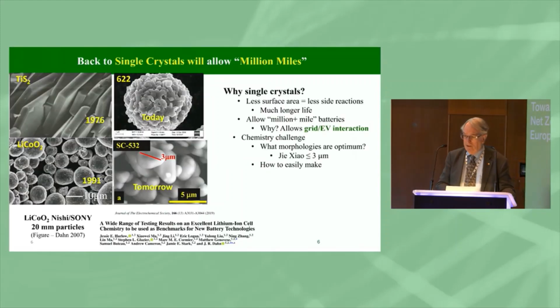Now, single crystals. What we're going to be doing is really going full circle if we do that. Here is Exxon 1976 single crystals. These we measured millimeters on the side, and if we wanted, we could make these centimeters. The commercial batteries all were millimeters on the side. Sony, for their lithium cobalt oxide, would try to make their particles as large as they could for safety reasons. Again, they want to reduce the reactivity. But then as we got into higher power devices, folks wanted more surface area to get a higher current out of it, and that's where these meatballs came in.